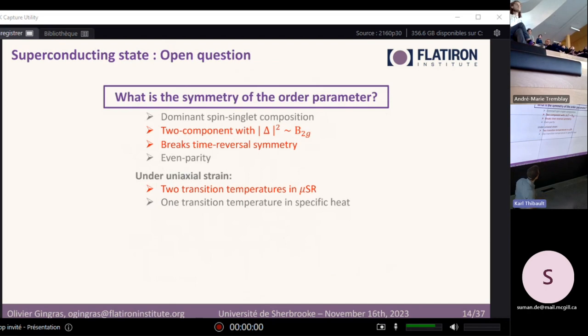So this is what we know on the superconducting state so far. It's mainly made of singlets. It seems to have two components that couple with B2g and break time reversal symmetry.